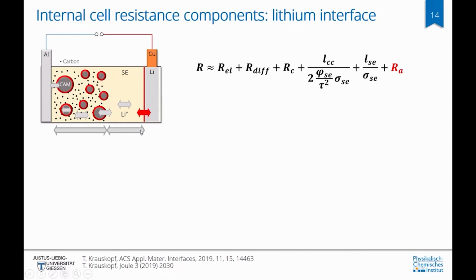And you may know our results, especially those by Torben Krauskopf from our group, who showed that the lithium at garnet interface actually has minimal or practically no interface resistance when this is prepared in an optimal manner. So you might wonder why I've highlighted this in red. Well, I think of the dendrite issues that still prevail with solid electrolytes, and especially the mechanical aspects at the interface, which need to be addressed.